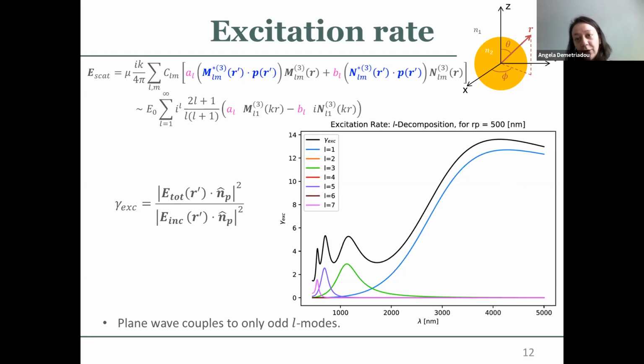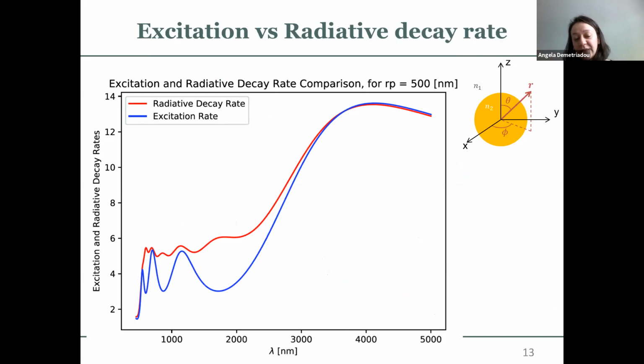I have a plane wave incident onto the spherical nanoparticle, a very large spherical nanoparticle. What I see is that I'm actually missing all the even L modes that cannot couple into my emitter, and they cannot excite it. And that's where the difference is coming from, a difference that you don't only see for the nanoparticle mirror system, it's actually something that you also see for very, very large spherical nanoparticles. And here I'm plotting both the radiative decay rate and the excitation rate. In red is the radiative decay rate, and blue is the excitation rate. And you clearly see that here you have the second order mode where you have a strong radiative decay rate, while for the excitation rate, you just have the value and there is no peak.